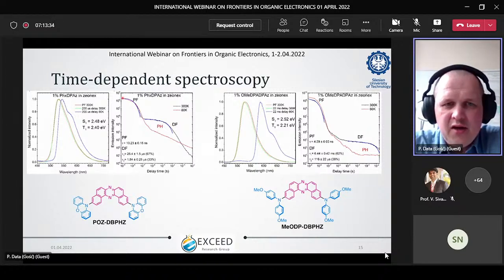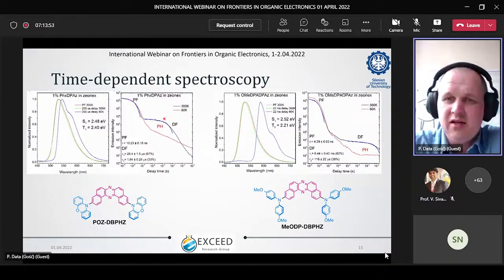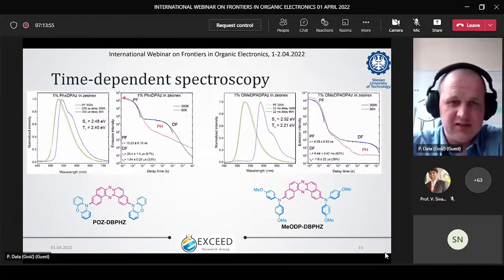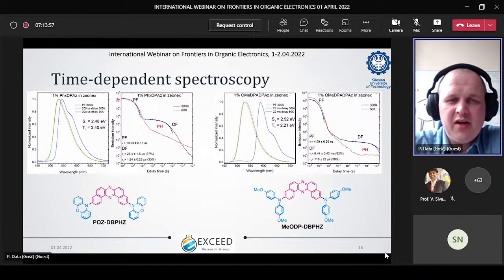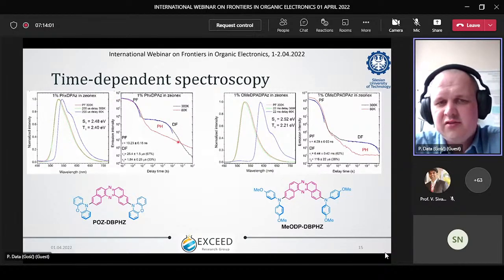So you have here a transient curve, but those curves actually are represented by spectra. At every point of the curve, we are obtaining spectra. So we can see how our spectra is changing at different temperature, at different delayed time from the excited state, laser excitation process. So we can see if we have phosphorescence, delayed fluorescence, or the phosphorescence process.